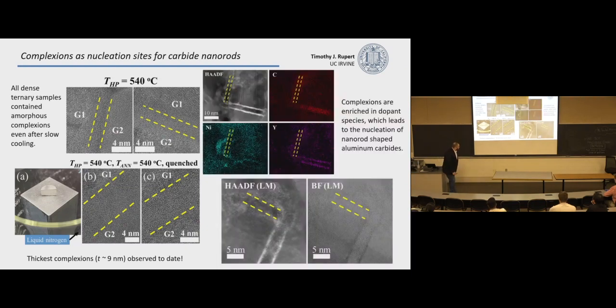The other thing that's pretty cool is that we're starting to see in this aluminum system that these amorphous grain boundaries can be nucleation sites for other types of features inside of our material. So we actually form these nanorod carbides that grow out of the amorphous intergranular films. Whenever you make these materials, you always have impurities, carbon, oxygen, things like that. In this aluminum system, these aluminum carbides want to form, and they nucleate here and grow out and actually increase the strength of our material. Here we're showing chemistry, here we're showing structure. You can see that carbide structure.